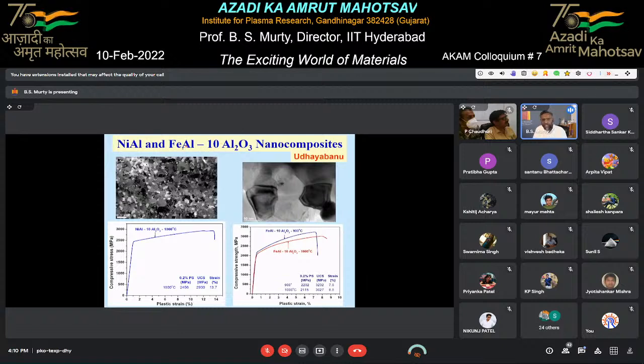We know that intermetallics are very brittle, and we also know that oxides are brittle. But when you make a nano composite out of them, you see that the strength is very high, 2500 megapascal, and it gives you almost 13 to 14% elongation. Usually these materials are brittle, with percentage elongation less than 1% typically, and you are able to produce wonderful combinations of strength and ductility by this kind of combination.